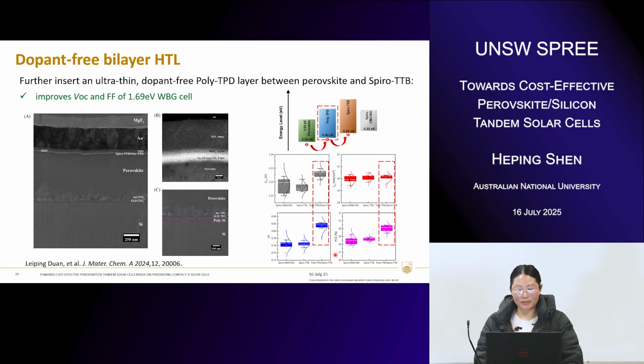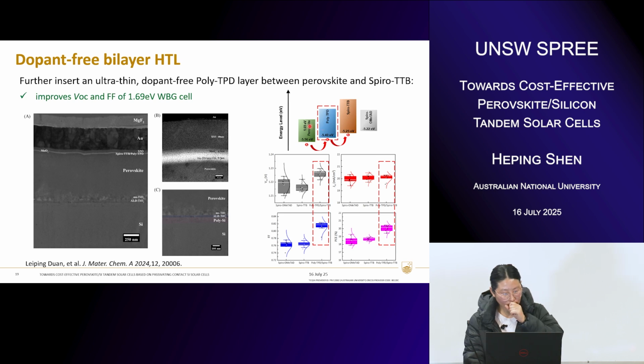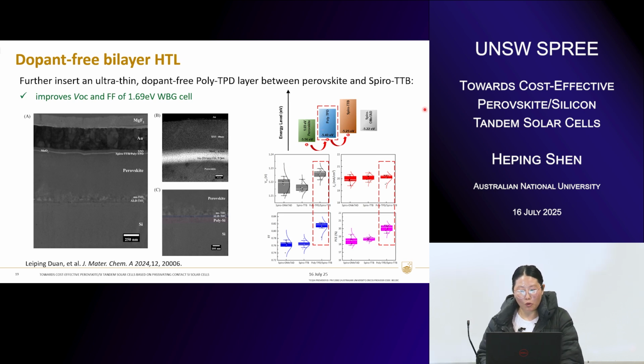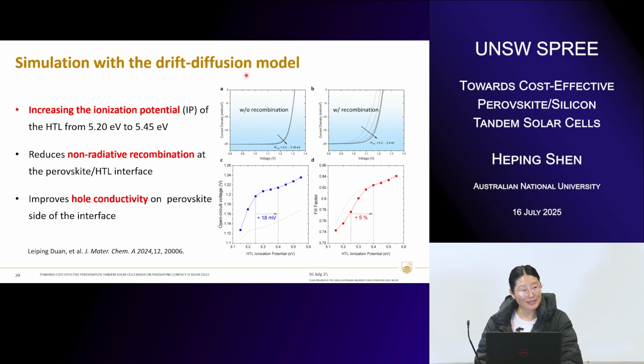which further improved the VOC and fill factor, which allows us to have better performance because of the better energy alignment here. As you can see, this is the perovskite, right? And this is the wider band gap perovskite we have, and this is spiro-OMeTAD. The valence band difference was relatively large compared to when we use spiro-TTB and poly-TPD. So then we moved on to understand how this energy level is important and benefits our cell performance. We again did a simulation to understand that. We found that the ionization potential of the HTL indeed impacts significantly the interfacial recombination as well as the hole conductivity at the perovskite and HTL interfaces.